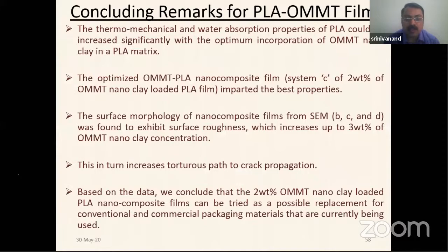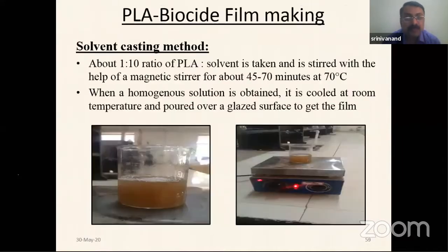The surface morphology we studied by SEM, which indicates surface roughness, which is very much required for fracture toughness. So we understand that PLA is no longer brittle when it is loaded with the organically modified montmorillonite. It becomes tough and stiff as well, and is able to offer a better set of mechanical properties which are needed by industries.